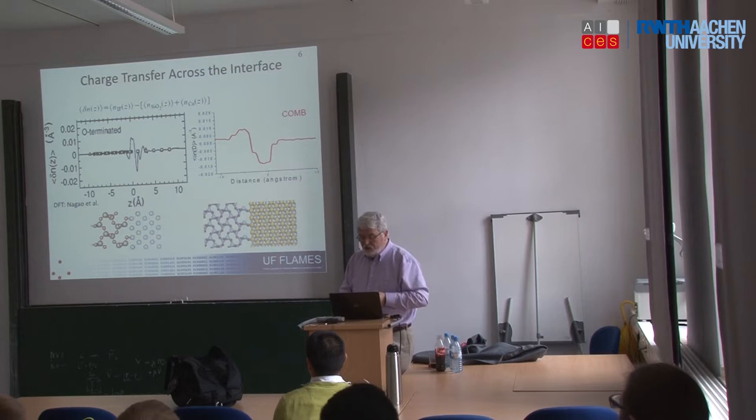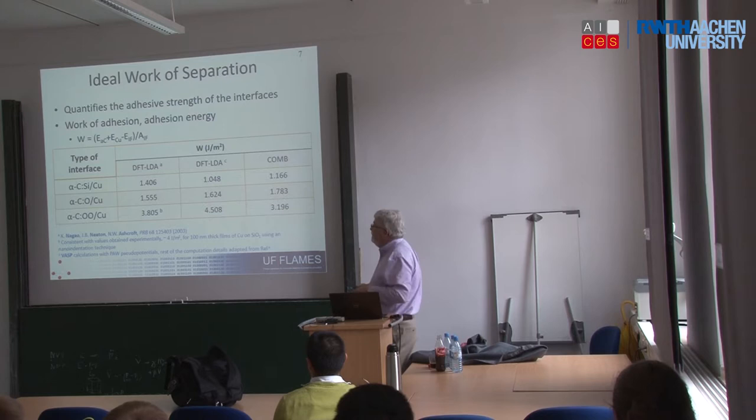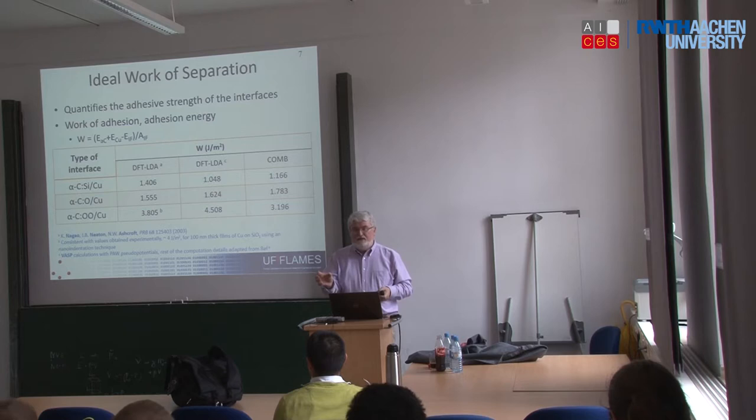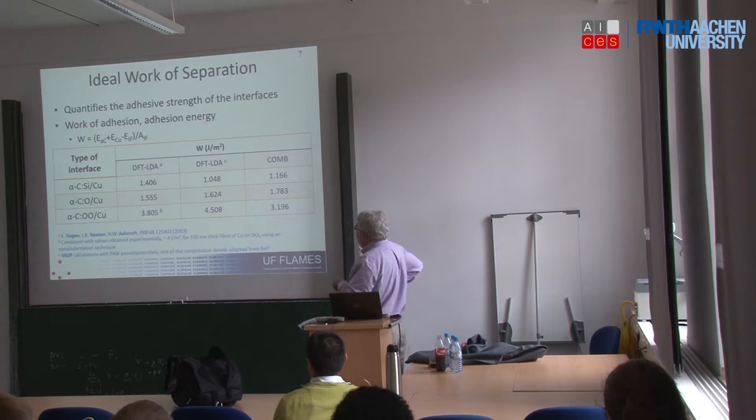Now we can get a little bit more quantitative on that. We can look at the ideal work of separation. So this is the cohesivity, the energy of cohesion. It's the energy of the structure of the interface less that of when you cleave the structure and you've got two free surfaces. So here's DFT LDA, and there are two different calculations here, and you can see that they are ordered in the same order that they increase from here to here, and the increase is somewhat over a factor of two.